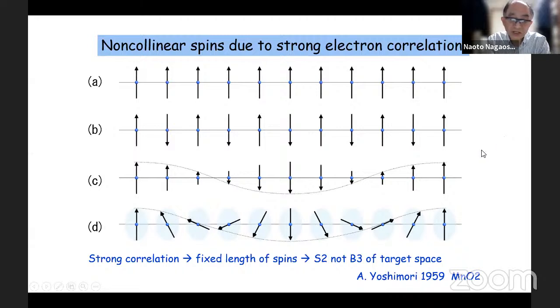But once you have a generic periodicity, if you keep the collinear structure, then you need to modulate the amplitude of the spin like that. But this costs Coulomb energy. The reason is that the strong correlation tries to keep the maximum length of the spins, right? And then in order to keep the length of the spins, you need to rotate the spin in this way. So this is the so-called spiral or helical structure. And then necessarily you have a non-collinear spin structure.